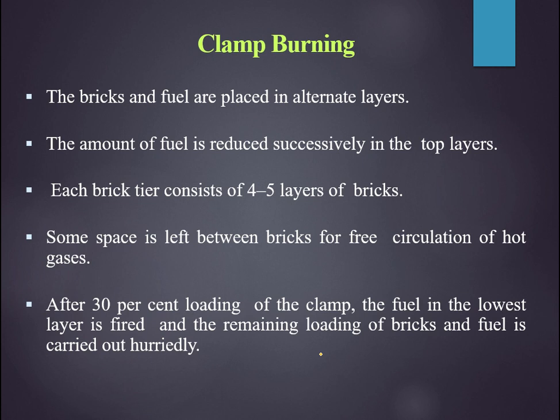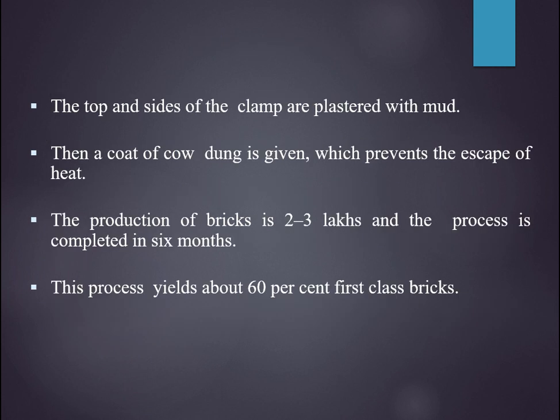After loading the bricks up to 30% of the total amount of bricks you have, you can start the fuel, set up the burning process, and then keep on loading the other bricks on the top surface. Remember, the clamp is generally constructed out of mud. We coat the inner side of the clamp with cow dung. Why? Because cow dung can retain heat. To maintain the heat inside, we coat the inner side of the clamp with cow dung, which prevents the escape of heat outside.